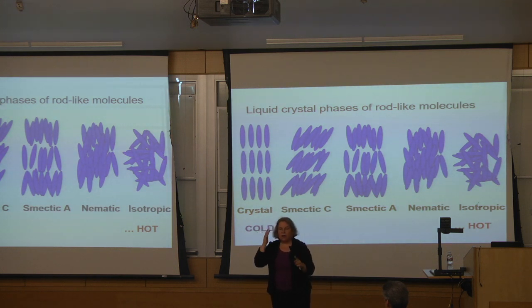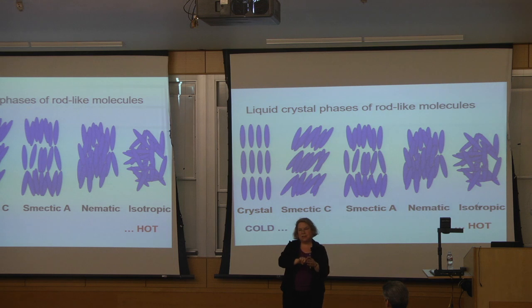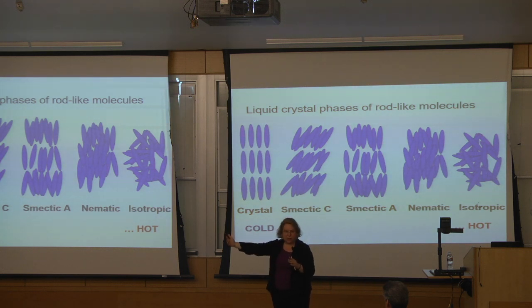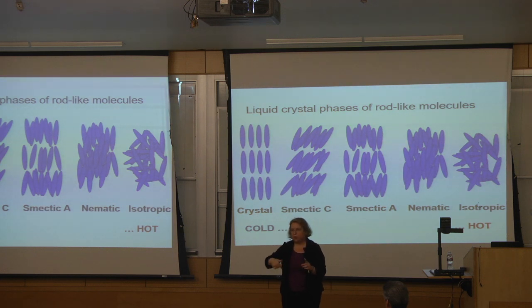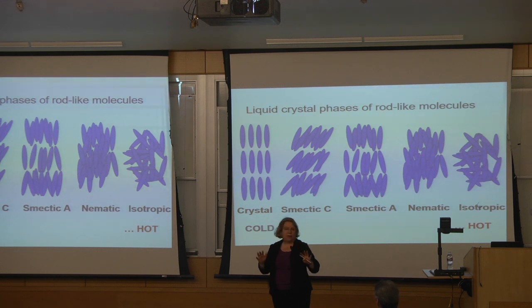So cholesteric liquid crystals, the distance over which they twist is very sensitive to temperature, and that's how mood rings work. The distance for a twist controls the wavelength of light that's reflected, and when it's warm, it's blue, and when it's cold, it changes. And actually, there are some chiral dopants where the distance decreases with temperature and some increase with temperature. So it's one of those great mysteries of life, how chirality occurs in condensed phase materials. It's really fun.